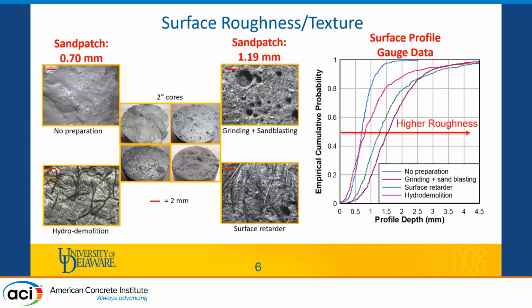And with the last 2 methods, the surface retarder and the hydrodemolition, they are comparable in terms of exposing the fibers. And it's worth mentioning that those fibers are exposed to corrode over time, especially since we left our specimens to cure for at least 28 days to limit the effect of the autogenous shrinkage. It's also worth mentioning that the fibers in the hydrodemolition are weaker because of the high pressure water that was used, approximately 34 KSI in this case.